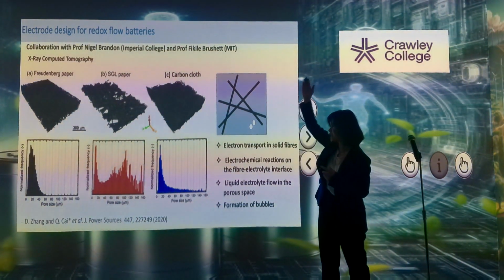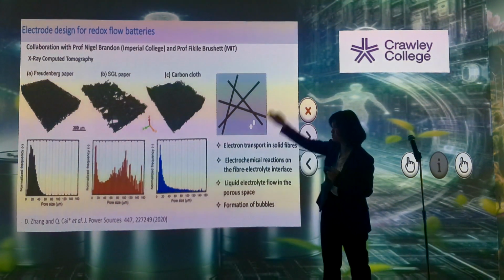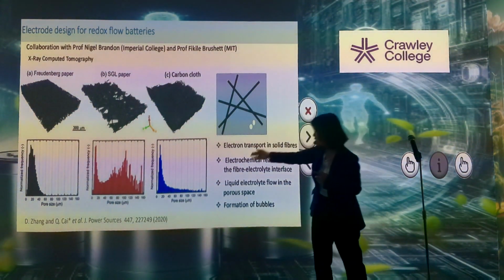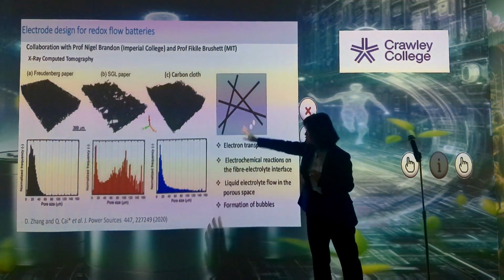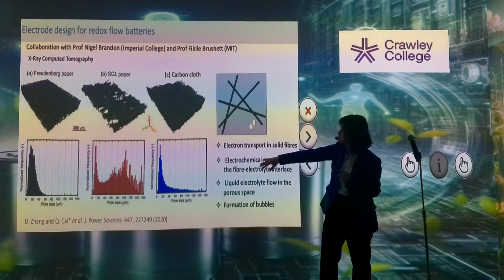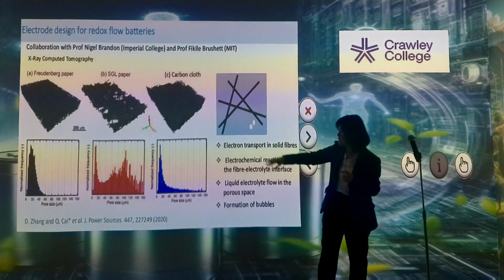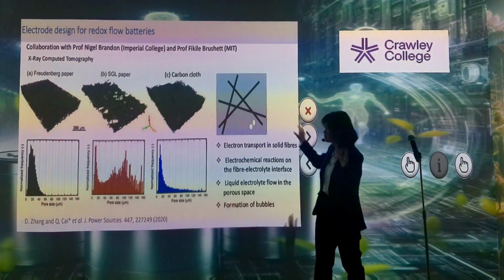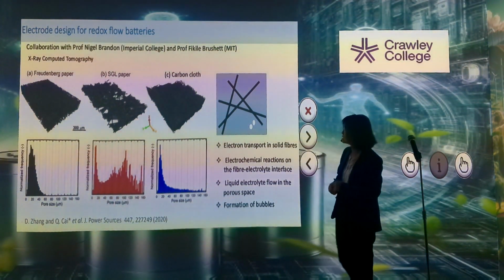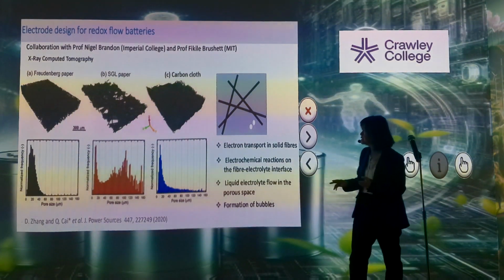Freudenberg paper has a very narrow pore size distribution, around 20 micrometer. Well, the carbon cloth also has a narrow pore size distribution, but it has a small portion of bigger pores. SGL paper has very random pore size distribution, and all these are going to affect their performance.